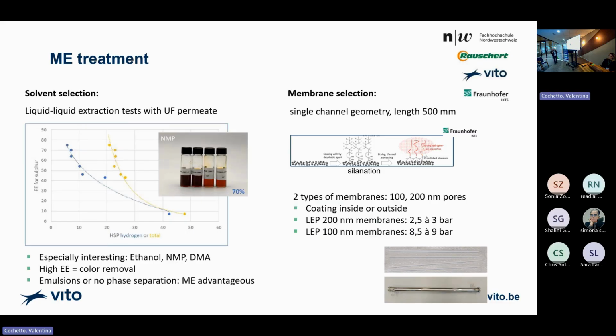How ME, it's based, of course, on the selectivity of the extractants. So the first thing we do is look for good extractants. So we tested a lot of solvents on the permeate that was created by UF. And we could even see a nice correlation between the extraction efficiency, I put it there for sulfur, but it's the same for other metals, as a function of the Hansen parameter, polar or hydrogen, total or hydrogen part. So the more apolar, the better it works.